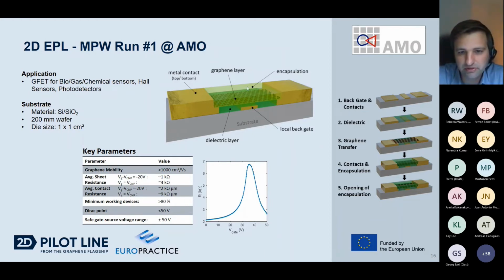The key parameters of this device are summarized here quickly. So we have a graphene mobility above 1000 square centimeters per volt second, and the average contact resistance in the range of 2 kilo ohms. And we have the Dirac point below 50 volts, and a safe gate to source voltage range of plus minus 50 volts.